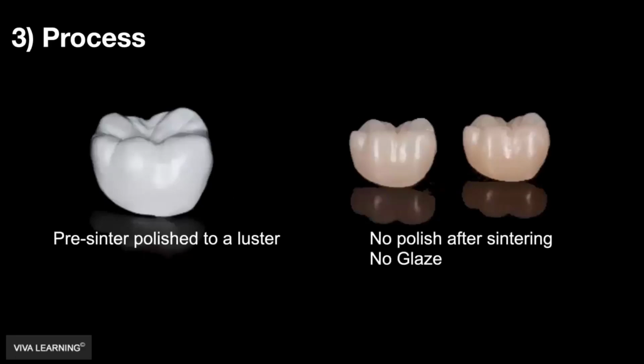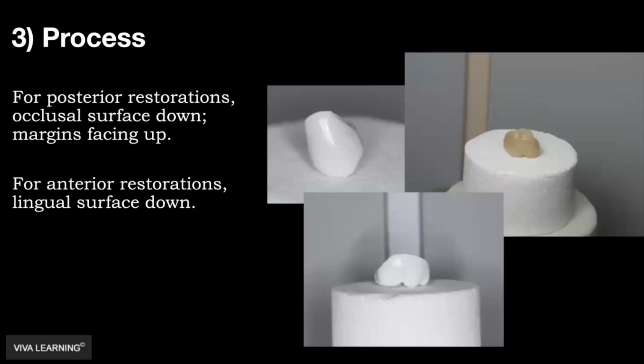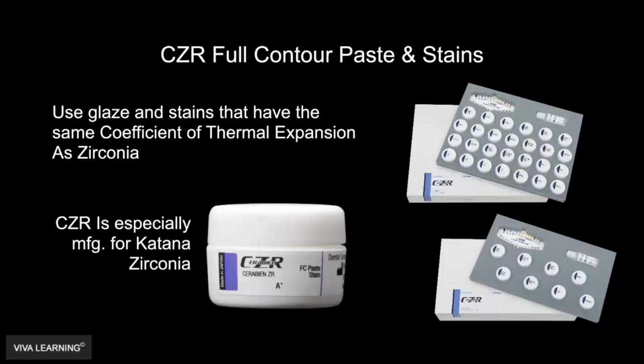Now, this is where we pre-sinter it. I use a very slow speed, slow RPM on a lab handpiece with some twist polishing burrs, and we can get some really good final prosthetics. When we go ahead and do need to sinter these restorations, remember, margins up, occlusal surface down. We do not want the margins touching this firing pad because it affects how it can sinter. So remember, margins up, occlusals down.